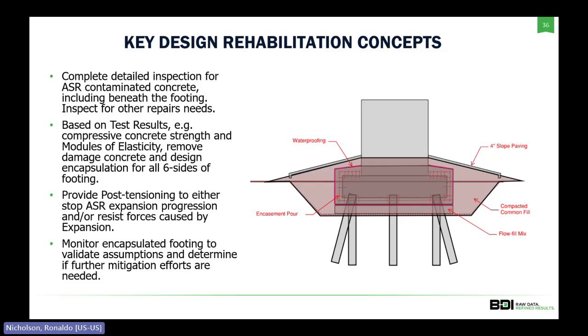First, we had to do a detailed inspection to determine the amount of damaged concrete. That inspection would require that we expose the entire footing. Some are currently exposed. Some would require us to excavate around the entire footing. And because the bottom of the footing had never been inspected, except through our coring, any evidence of the level of impact of that concrete, we needed to have access to the bottom of the footing as well. The footing is supported on piles, so our conceptual and final design included excavating underneath the footing so that it can be inspected and damaged concrete could be removed.